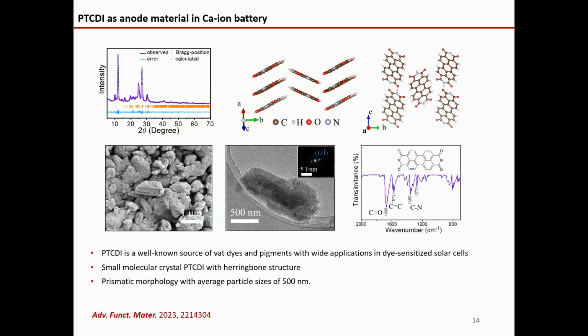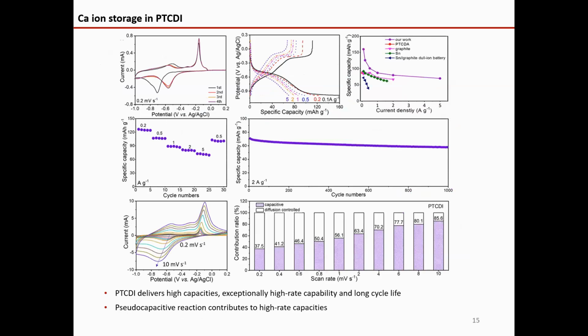Okay, so these are the characterizations of this material, XRD and SEM. You can see these are the as-received material. We don't treat it any further, and the carbonyl groups in this functional material are possible to allow the storage of calcium ion. Luckily, when we test the material in calcium battery systems, we find that, okay, so good.